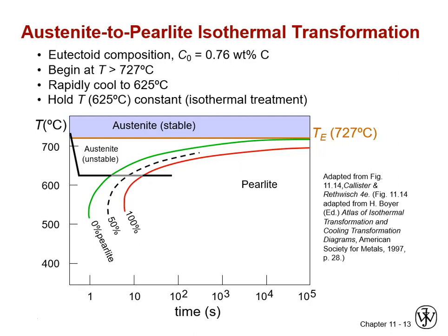We were all pearlite. So same composition, same phase diagram. All we did was we gave it another 50 degrees of undercooling. And I could just about guarantee you that the pearlite I formed from this one was finer than the one that we formed at the 675 hold.